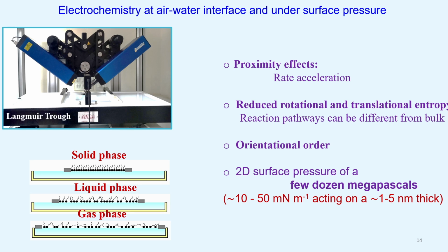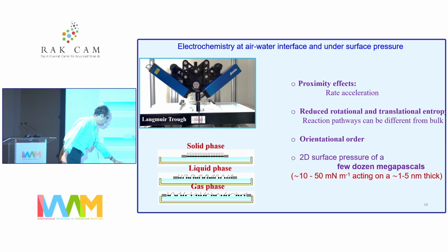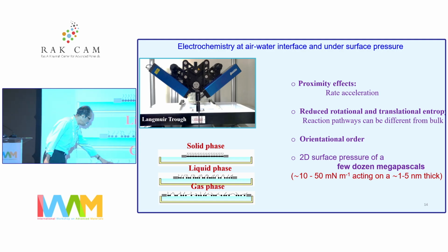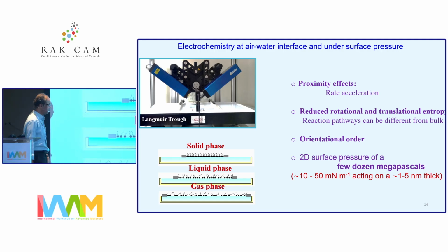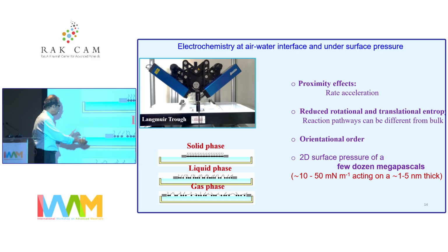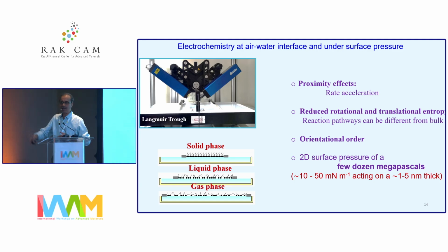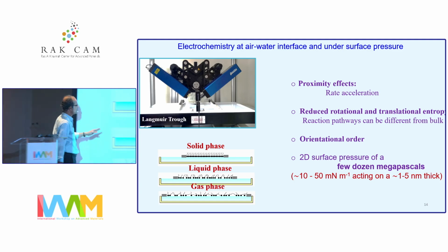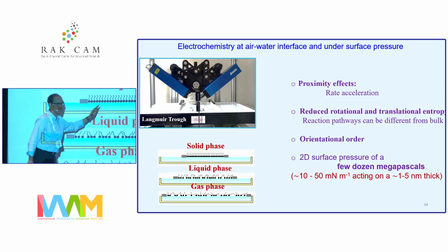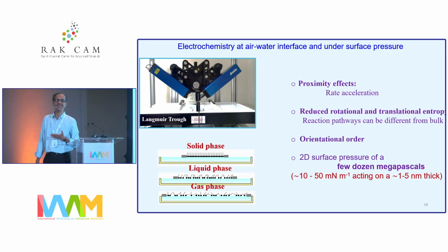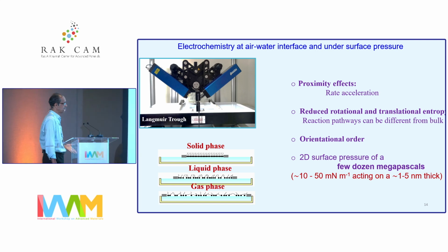Essentially, our system is a Langmuir trough wherein we have a molecule stabilized at the water-air interface. The moment I have this kind of surfactant, the molecules have all kinds of orientations, and I start to compress them at this surface. They start to have a little interaction, and subsequently you start to have a solid phase. So this pressure-area isotherm is something that we can follow to understand what exactly happens as far as the pressure is concerned.